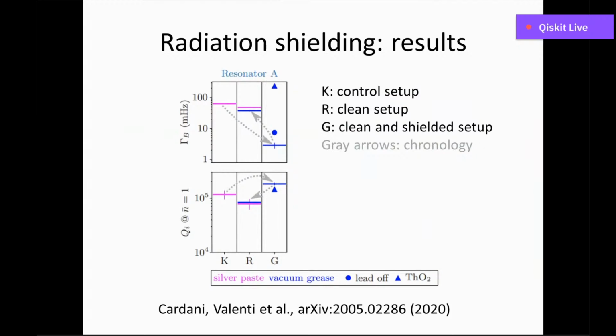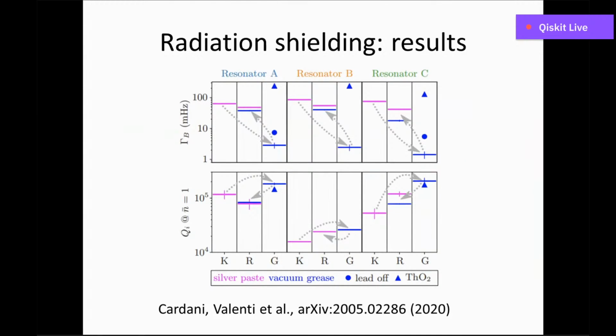And for the same resonator, this is the effect on the dissipation of the internal quality factor. We see that by cleaning and shielding, we again see a beneficial effect. We see a reduction when we add the thorium oxide source, while when we measure in the clean setup, it's not clear why we get a lower value with respect to the control setup. However, if we look at all the resonators, we see that what is consistent is cleaning and shielding always improves the amount of bursts that we observe. It reduces it by up to a factor of 50, and it always increases the internal quality factor up to a factor of 4.